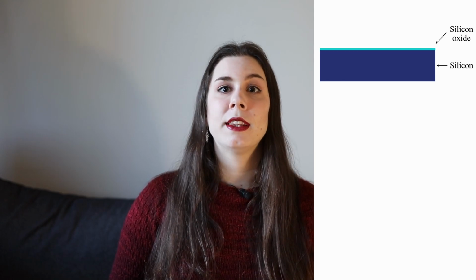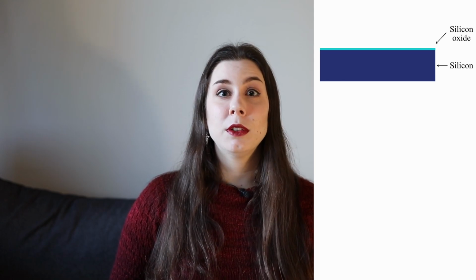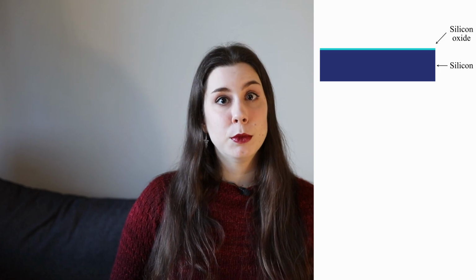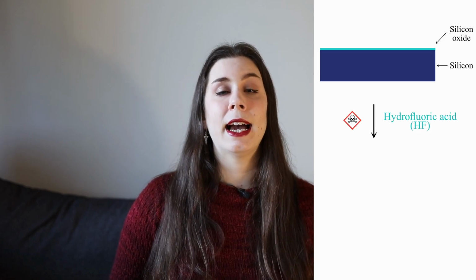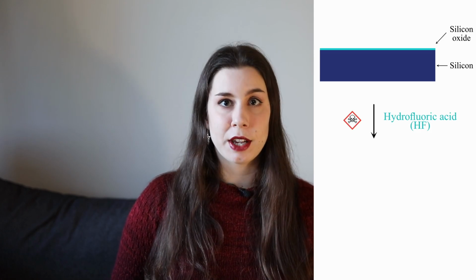The first step in our process is to clean the surface of the silicon wafer before we deposit the superconductor on top of it. The thing is, a silicon wafer, if left for long enough in ambient air, will inevitably grow a thin layer of silicon oxide on top, which we don't appreciate in our devices, so I'm going to remove it by drowning the wafer in hydrofluoric acid, also known as HF.